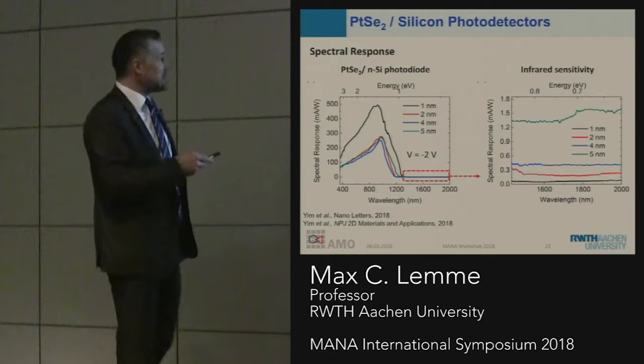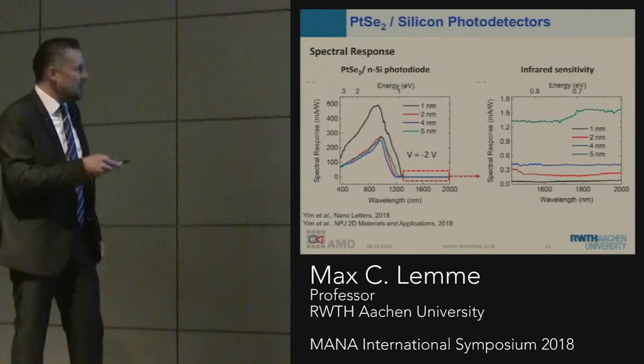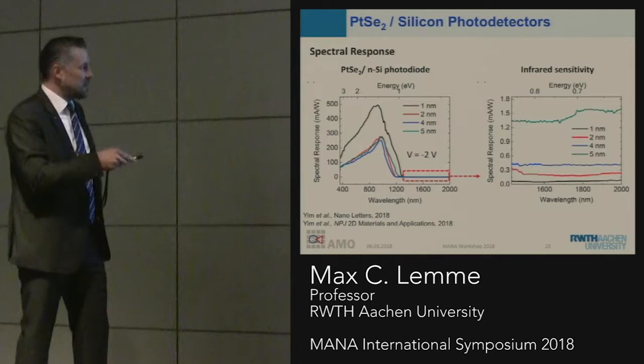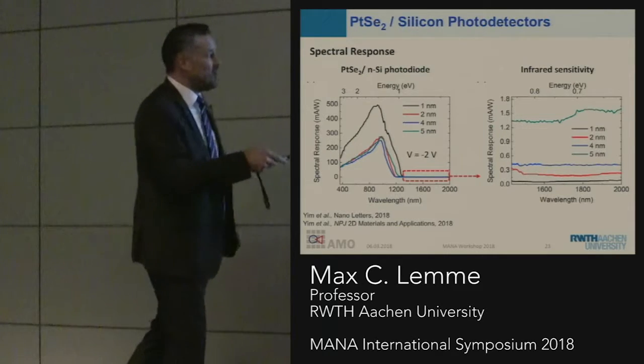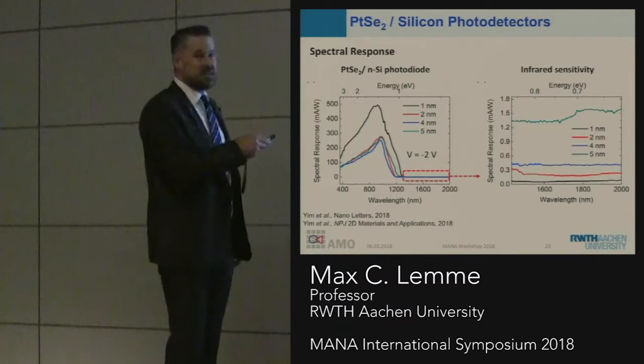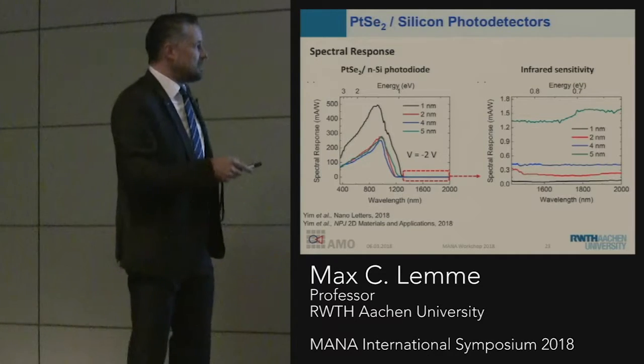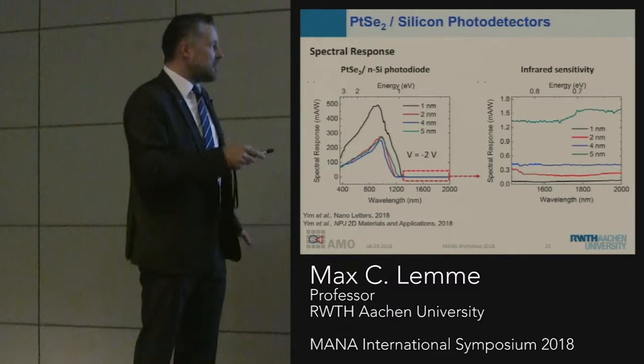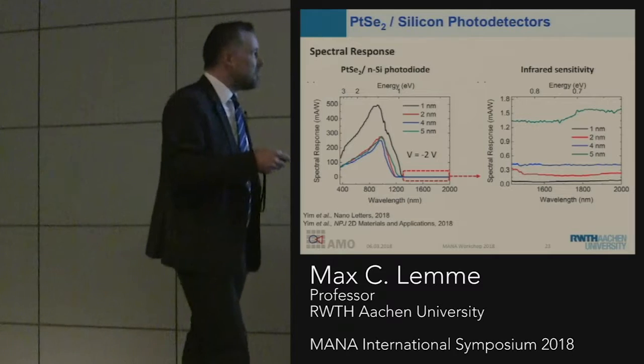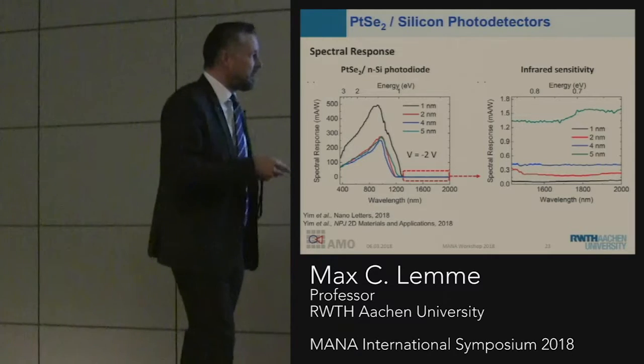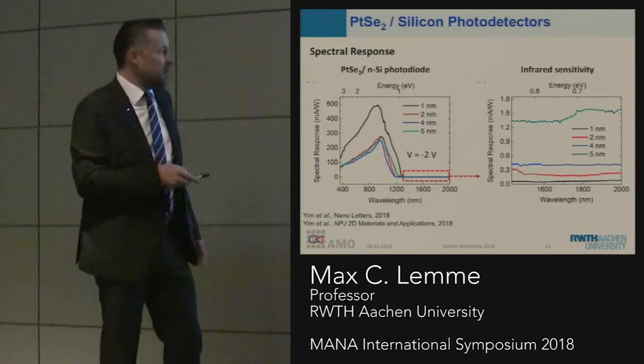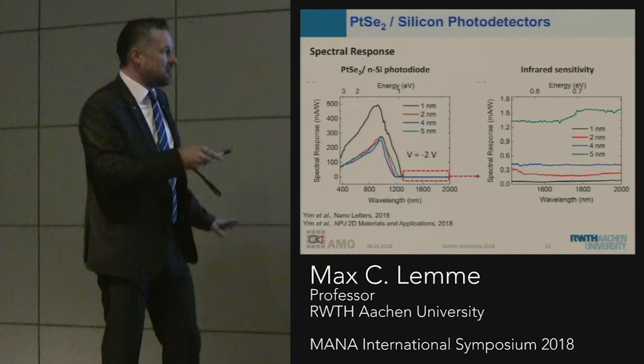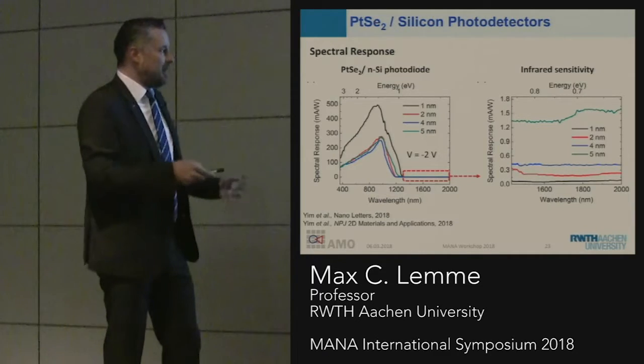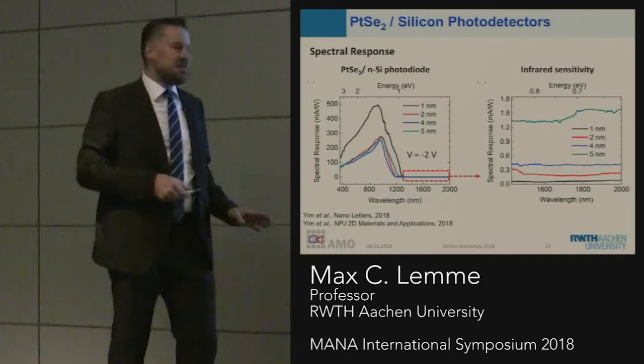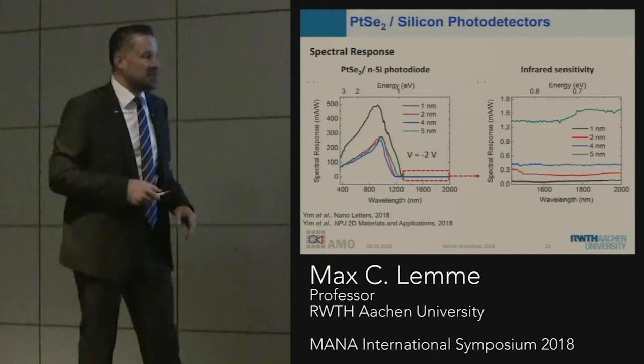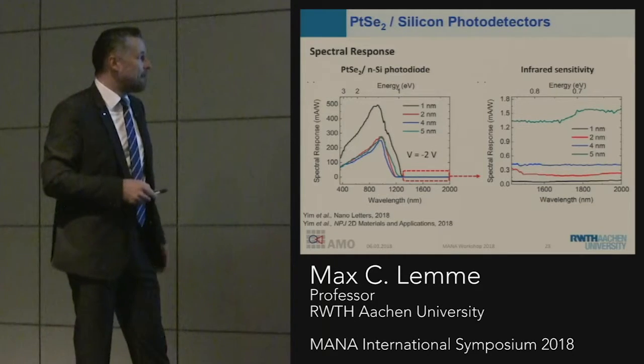Here we go. We also did similar diodes with platinum diselenide. Again, you see the silicon signature here, and in the infrared region you see the absorption, because platinum diselenide is also a semi-metal. And here we get up to almost 2 milliamps per watt, depending on the thickness of the platinum diselenide. So again, we can make photodetectors that work in the infrared with bad efficiency, but I think it's still an interesting thing to look at in the future.